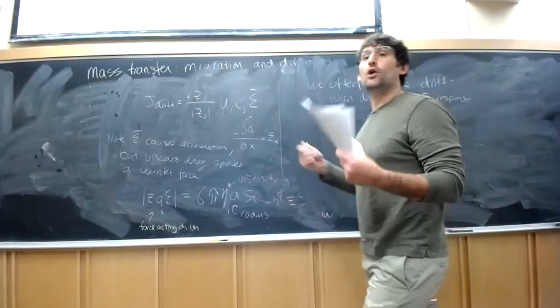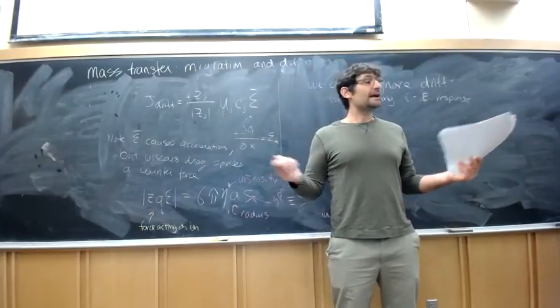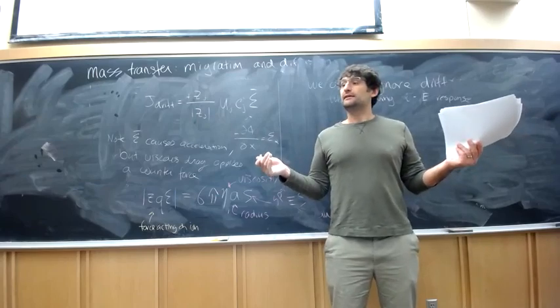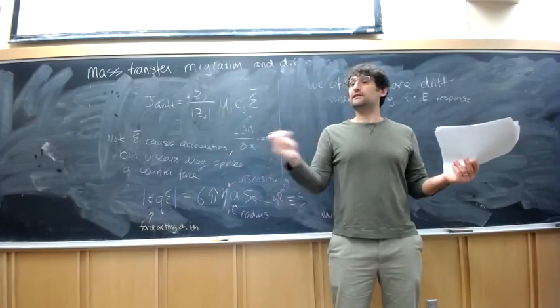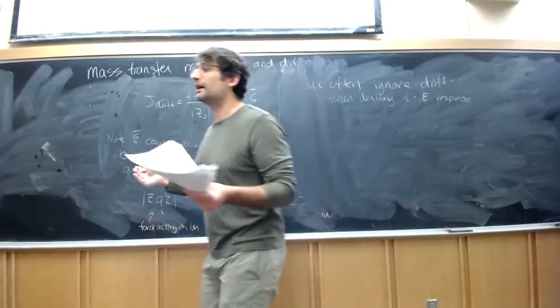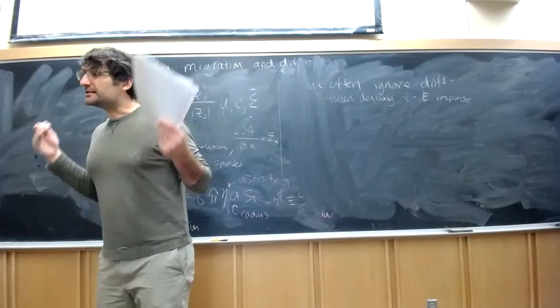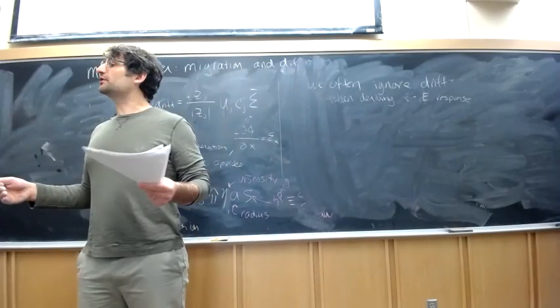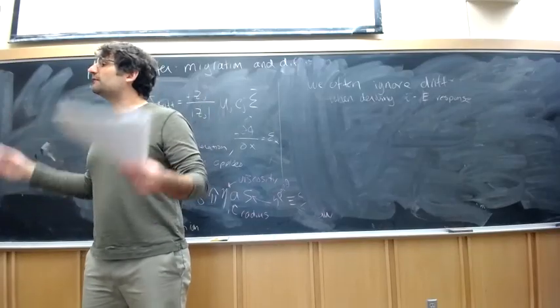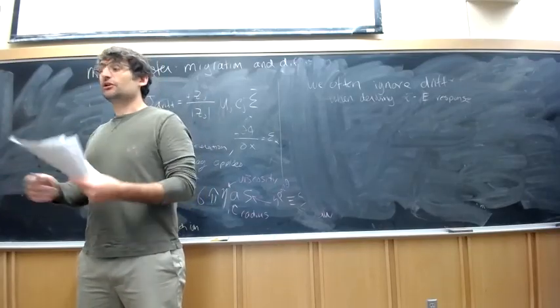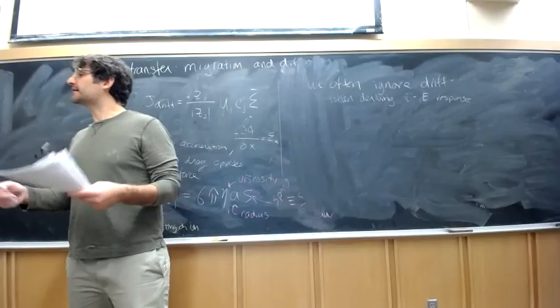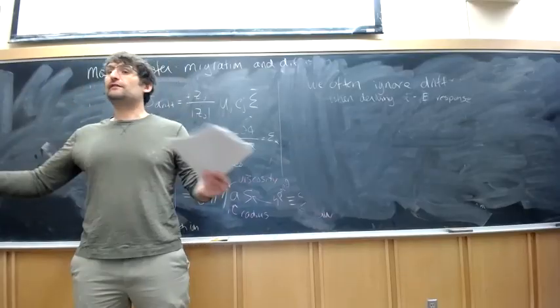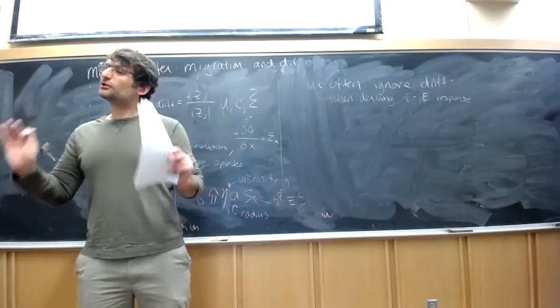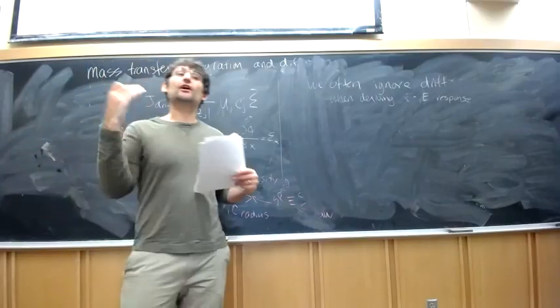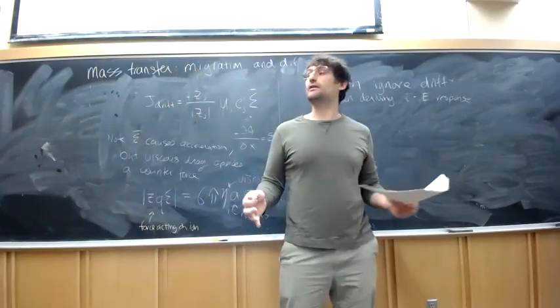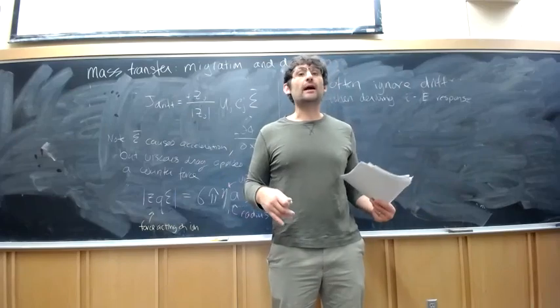Because if you imagined if O and R were charged, which they often are, and there was a big field in your electrolyte, that field might cause them to move too. It might not just be diffusion, but we didn't ever talk about the field when we derived the i-E curve, right? And that is precisely because we have so much supporting electrolyte that that field is kept very small. Because you have a high concentration of mobile ions that can move, that basically screens any field that might develop in the bulk. But there always has to be some, and if you go to very high current densities, it becomes very important, like in an electrolyzer, for example.